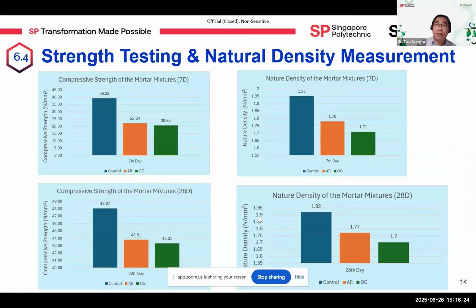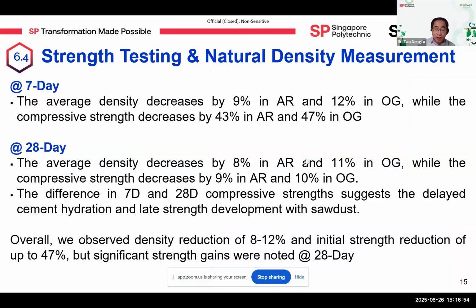Three cubes, of course 50 by 50 by 50 mm, were cast for each mixture to evaluate the strength, density, water absorption, and void ratio. Both 7-day and 28-day compressive strengths and natural densities were measured for the control mortar and the mortars containing sawdust, namely AR and OG. The bar charts here present the test results for compressive strength and natural density of the mortar mixtures at 7-day and 28-day curing periods.